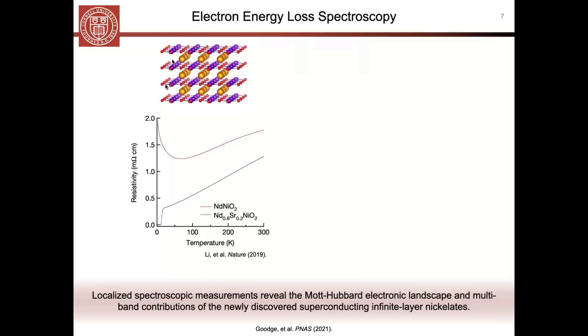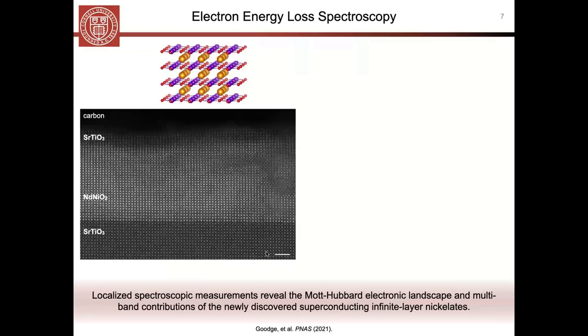And so it's sort of the perovskite structure with the oxygens and the rare earth plane removed. And so you can see here that with the right doping, there's a superconducting transition down around 15 Kelvin. And so what's kind of unique about these superconductors compared to other discoveries that have been made in the past is that they have, at this point, only been produced in this very thin film geometry.